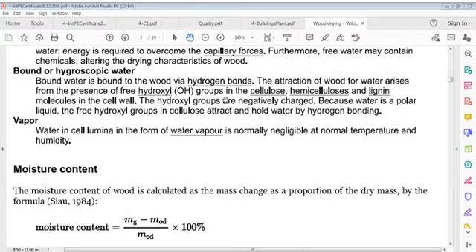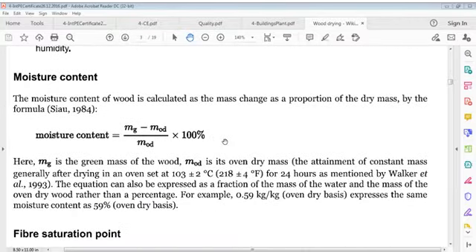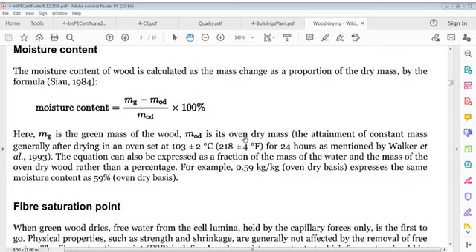Moisture content. Moisture content of wood is calculated as mass change as a proportion of dry mass. So you can say the formula is moisture content equals (mg minus mod) over mod, times 100, where mg is the green mass of wood and mod is the oven dry mass. So you can say green mass minus oven dry mass. Attainment of constant mass is generally after drying in an oven set at 103 plus or minus 2 degrees for 24 hours, as mentioned by Walker.